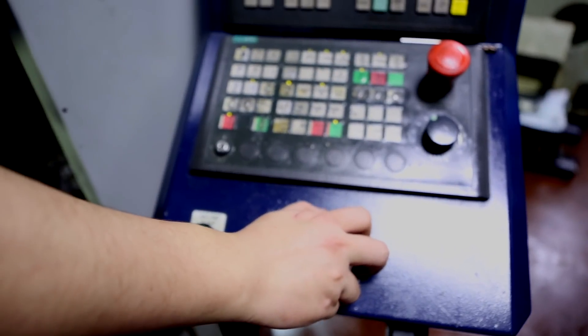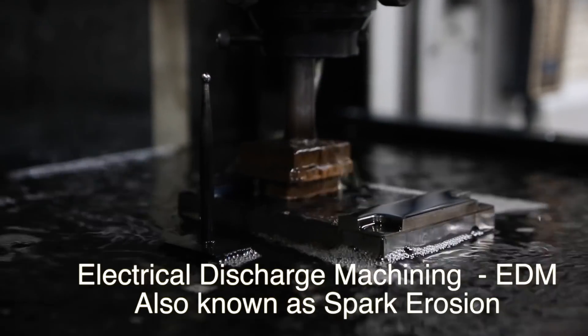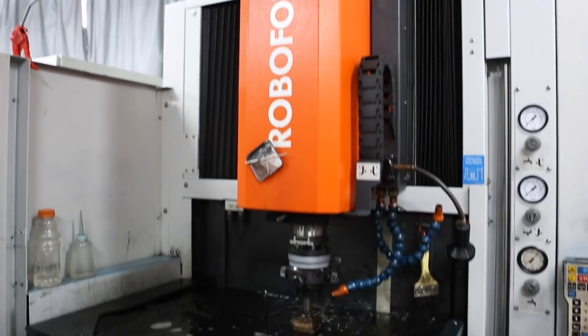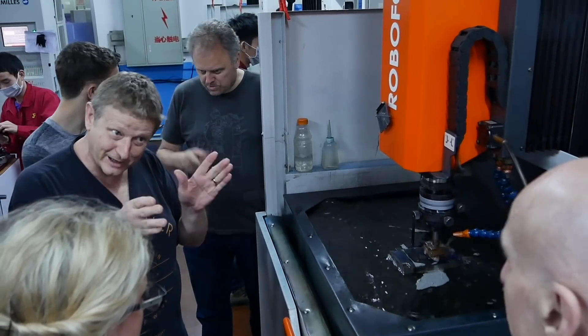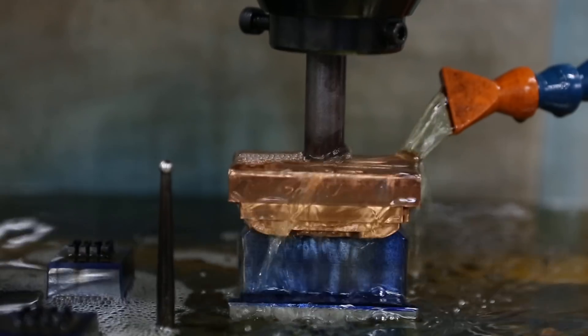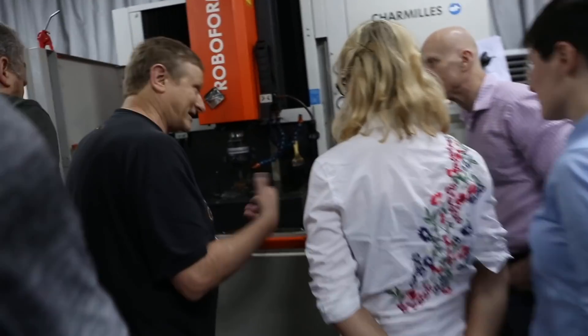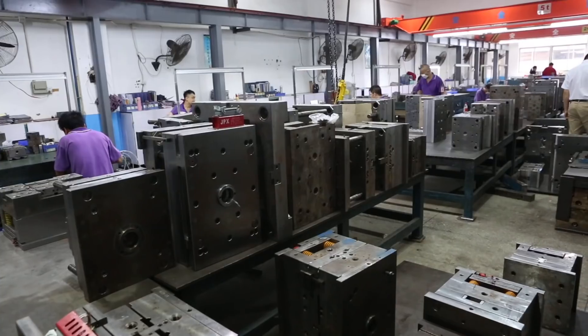After machining out the negative of the physical product, it goes to the next process which might involve EDM or spark erosion. In spark erosion, they make a model of the part and a machine very slowly etches that part out of a piece of tool steel — atom by atom removing material. The spark erosion machines can take many days if not weeks to gradually etch out very fine patterns. The machine holds the master over the top of the tool steel, water flows through it, and an electric current removes very small portions of the steel only a few atoms at a time. The result is a tool made out of extremely hard steel capable of producing a very large number of parts.